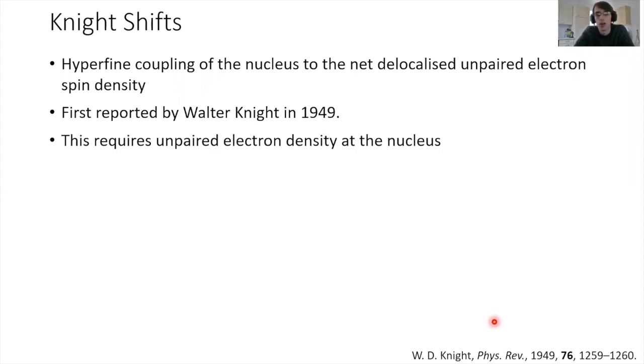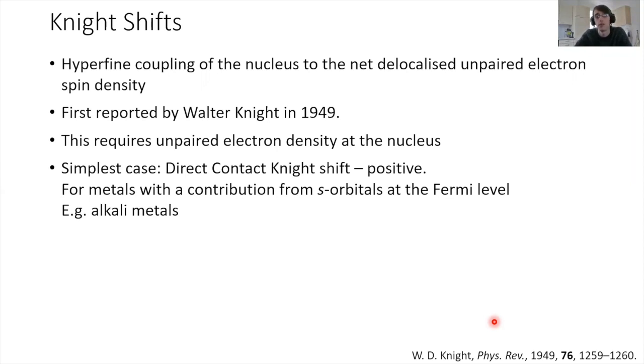And what it requires is that there's some coefficient of the unpaired electron density at the nucleus. The simplest way this can happen is if we have s orbitals. So s orbitals are the only orbitals which have a coefficient at the nucleus. And so if we have valence s orbitals that are partially filled at the Fermi level, then this gives us a Fermi contact, and this gives us a positive shift, which is known as a direct contact Knight shift. And this is the case in alkali metals, for instance.